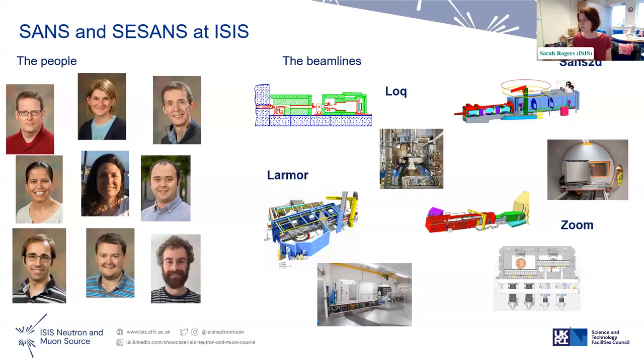Not only did we vary lambda, we can also vary theta by changing the detector distances. So if you're interested in stuff that's very small, we can push the detectors closer, so you get the flux back. If you're interested in stuff that's large for neutrons, then we can push the detectors far away. So we can basically tune the instrument to the size regime that you're interested in.